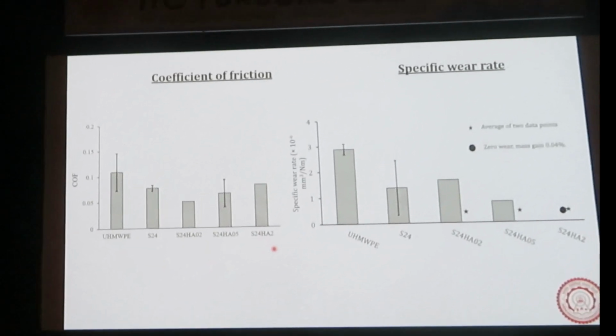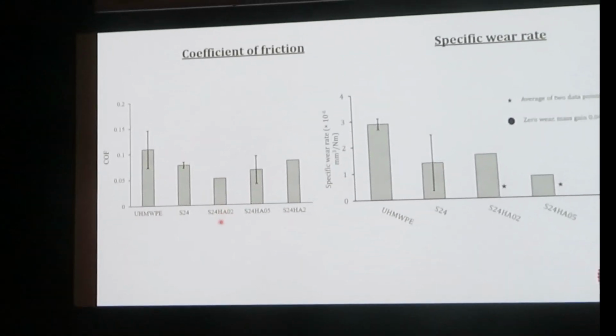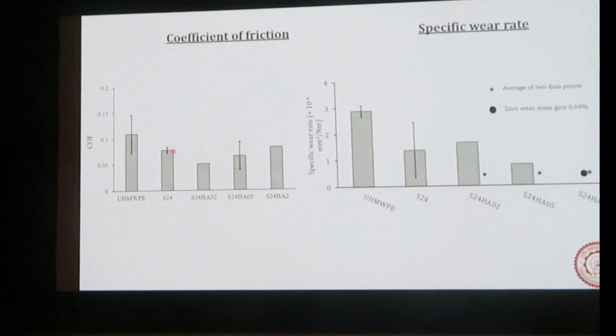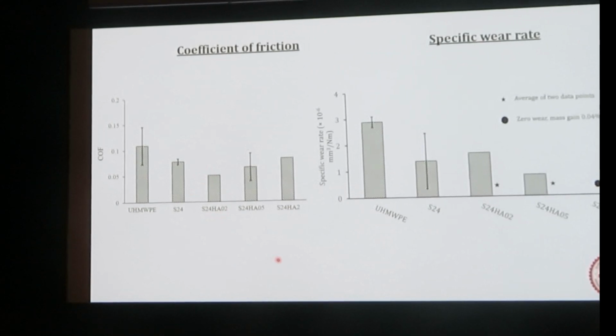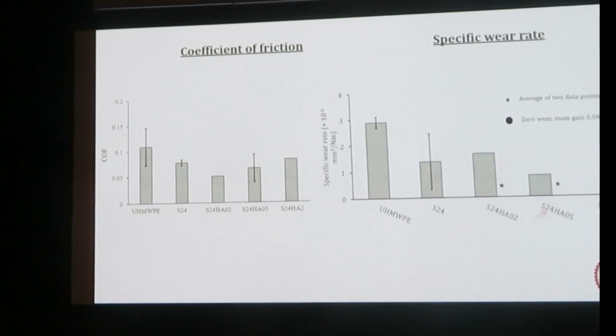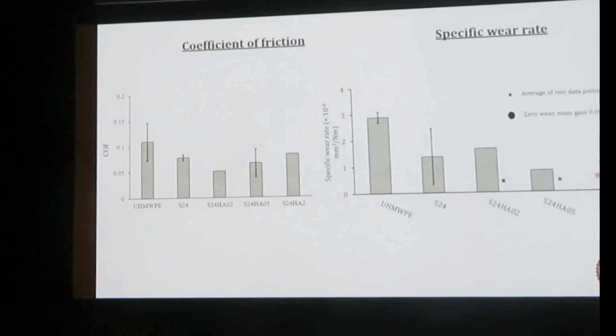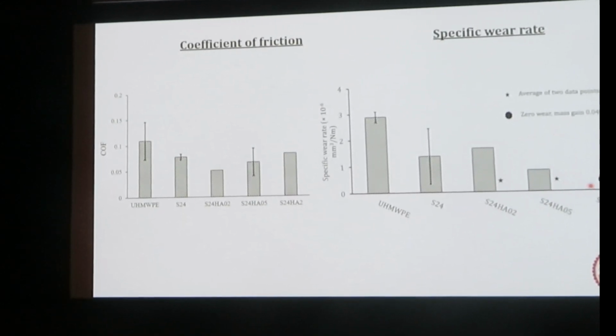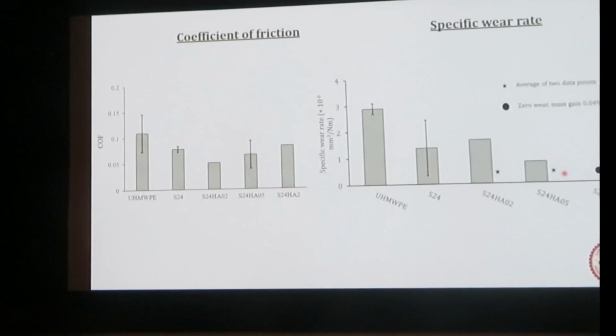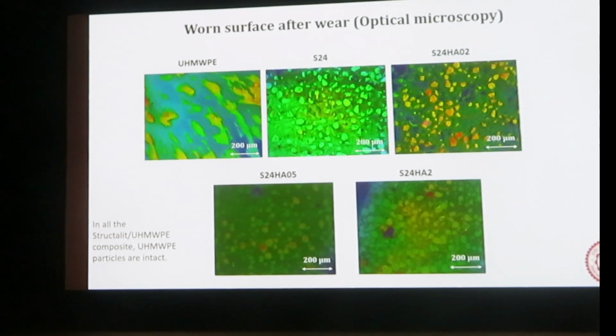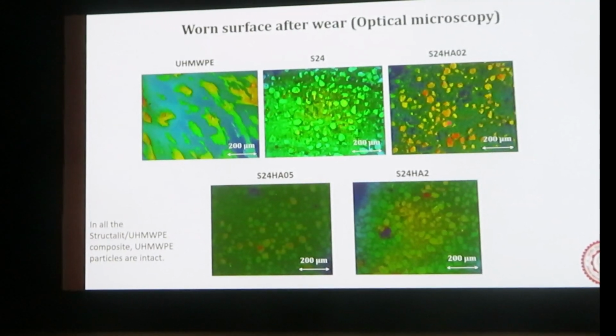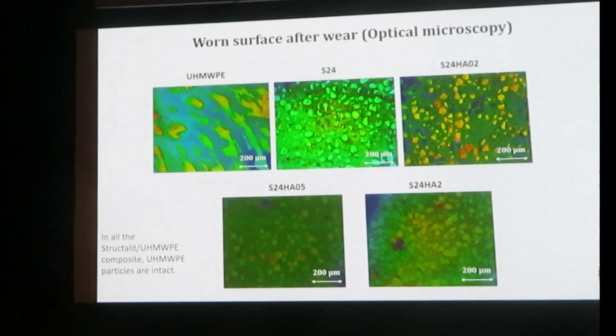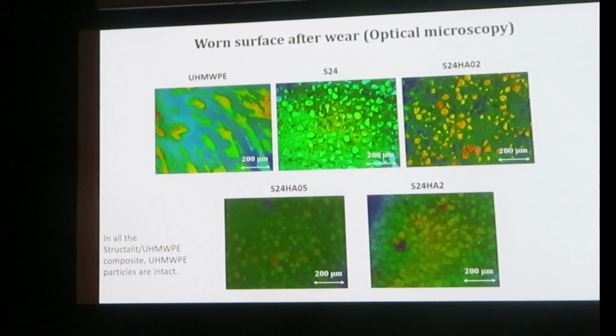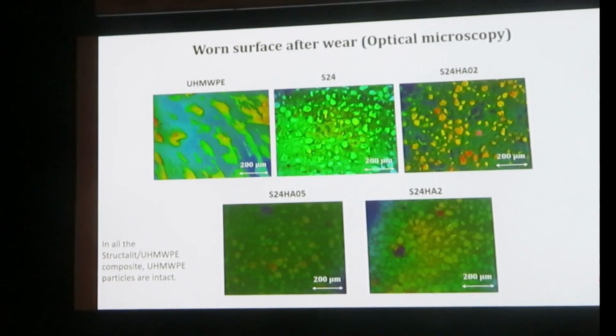Then we added HA into it, HA as a lubricant, and in the presence of HA, we get even better results compared to without HA. So this is without HA, and this is with HA. This work is still in progress. For example, these data are still not verified with many repetitions. These are only 2 repetitions. But we see a lot of good promise here. These optical micrographs show how the UHMWPE particles are bonded in the matrix after the wear test, and you can see that there is hardly any removal of the particles. They are fully integrated.